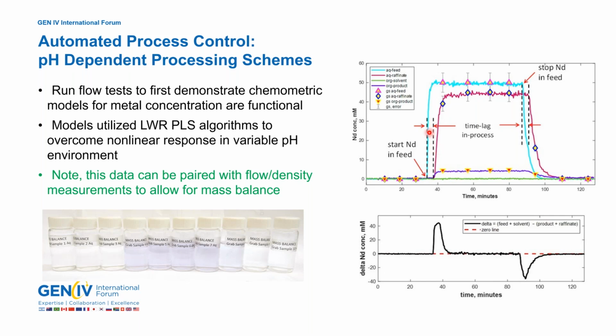Now notice here that there's a delta in time from when we observe the neodymium going into the feed at the inlet of the contactor, and there's about a 5 to 10 minute lag before we see it coming out in the raffinate and the organic stream. That's because there's some neodymium in process. It takes a while for the neodymium to work its way through the centrifugal contactor before it comes out to either the raffinate or the organic product. And we see that down here.